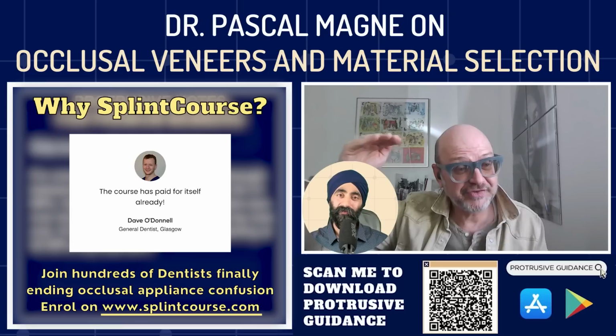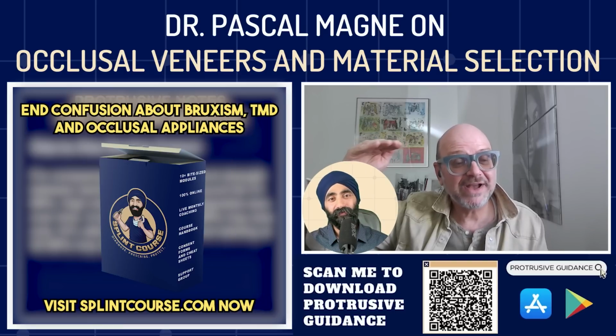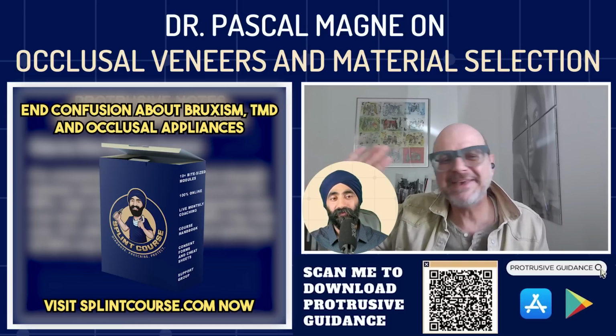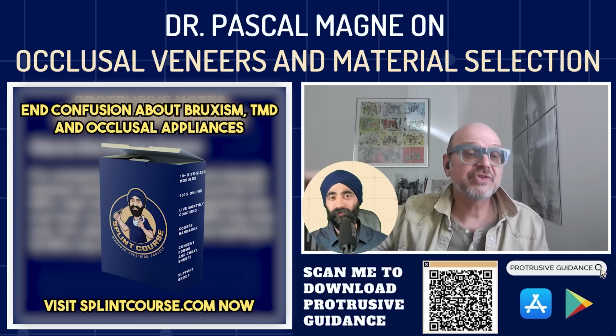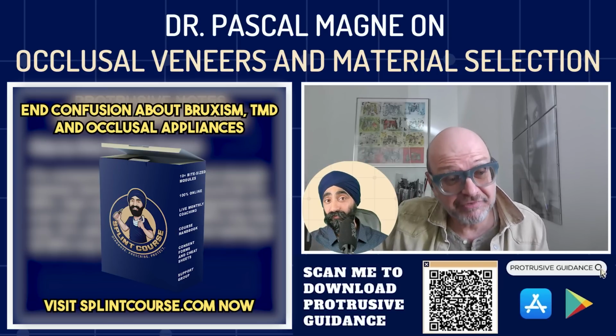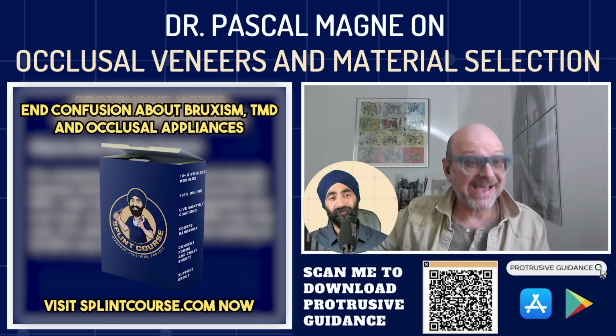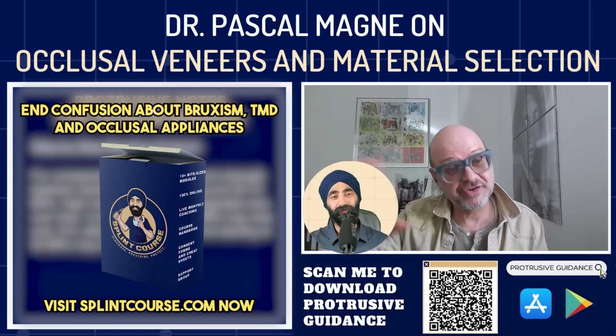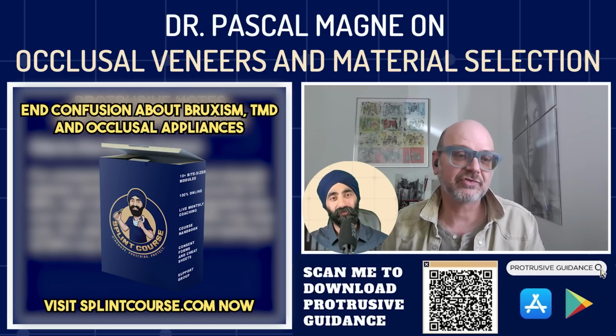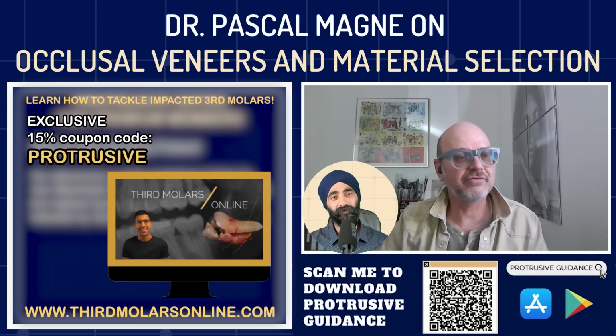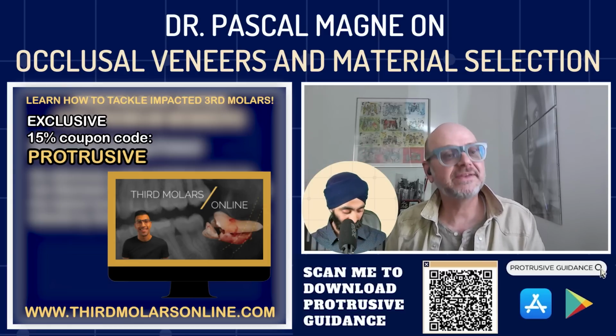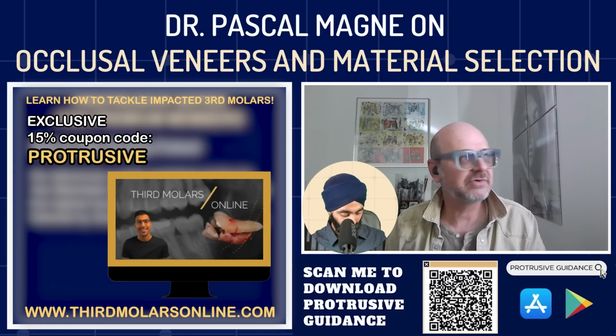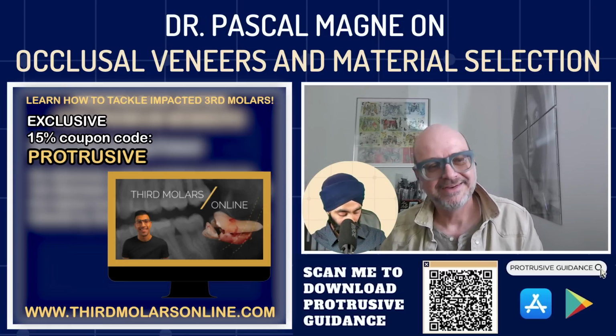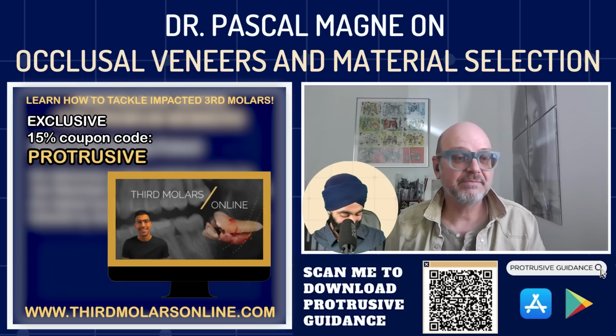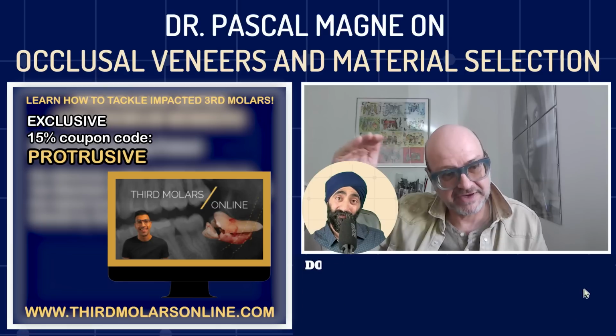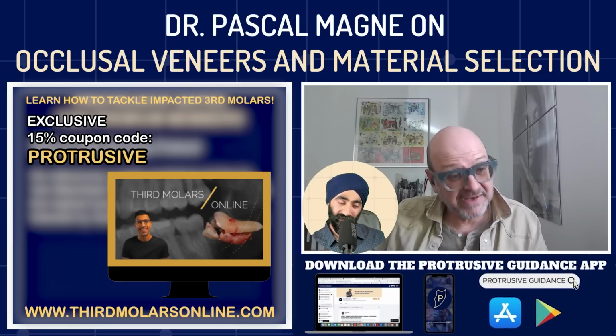If you start at 58, maybe 1 year later, you lost maybe at worst 10%. But when you start at 35, 1 year later, you lost at least 30%. And that's one of the studies by Van Meerbeek, demonstrated in a meta-analytical review of all the adhesives studied on the market. It was about 10 years ago. Number one was Optibond FL. Number two was SE Bond, with not only the highest bond strength, but the best stability of the bond.